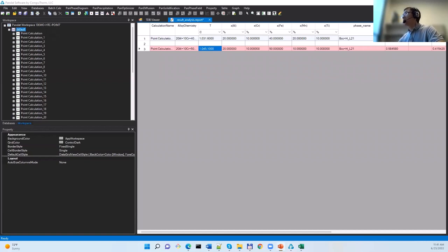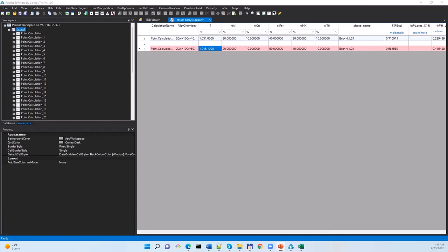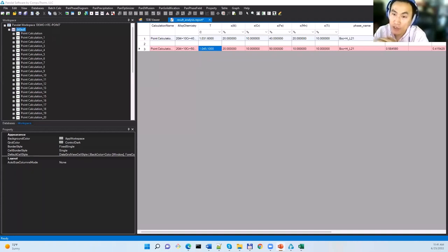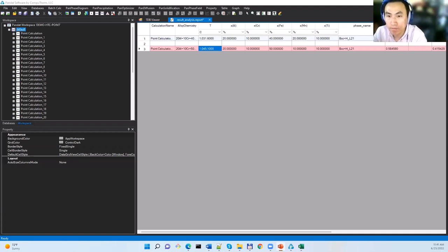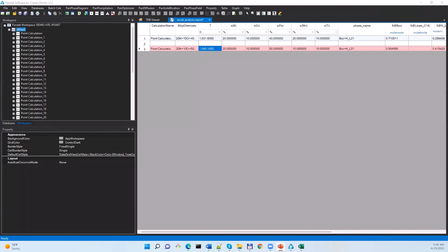There are a couple of questions in the chat. One is how to improve back diffusion of elements in the shell model. We cannot do that in the shell model itself — you can use our PAN Solidification module, which already includes back diffusion effects of elements. For fast diffusion elements such as interstitial elements like carbon or nitrogen, we would need to consider a parallel equilibrium combined with the shell model — that is planned for future development.